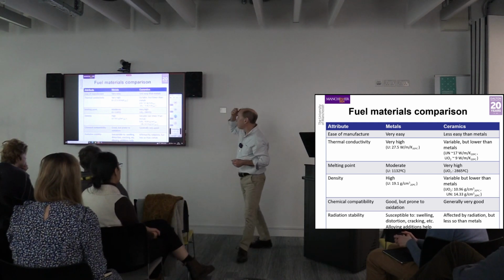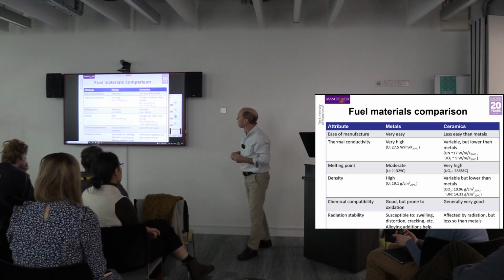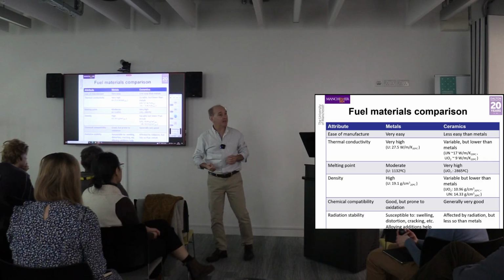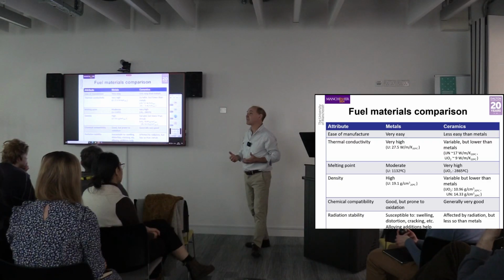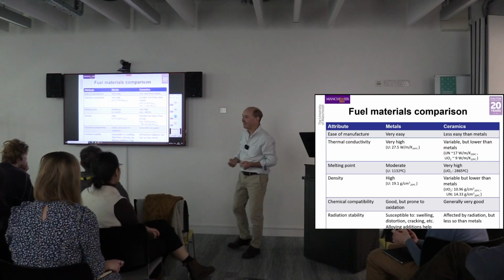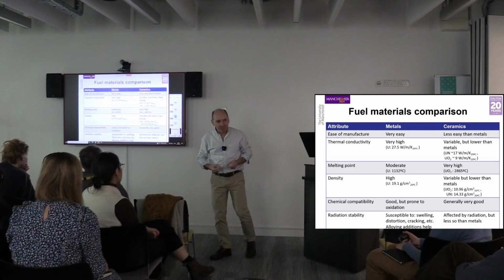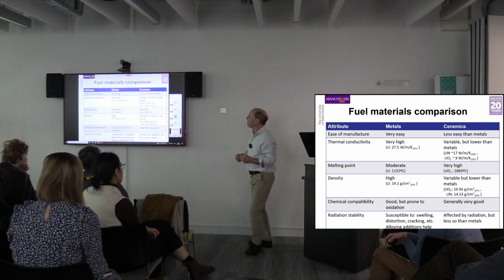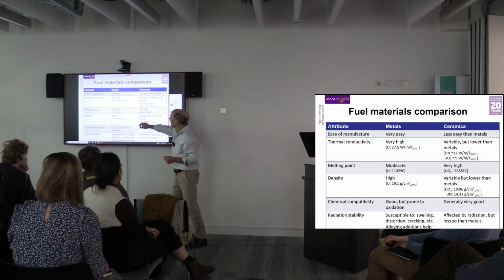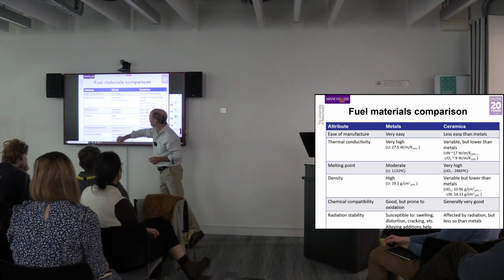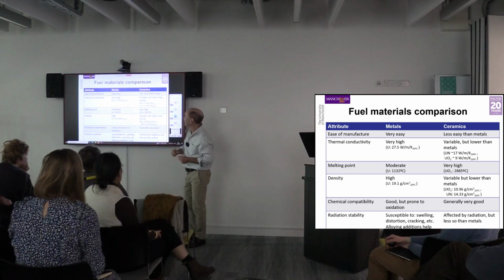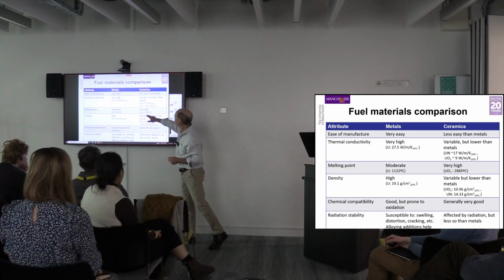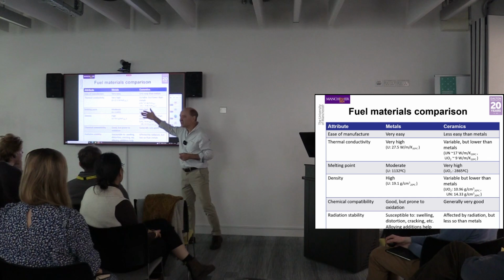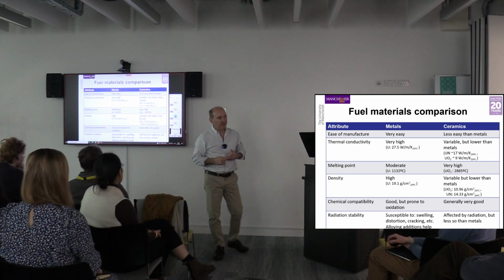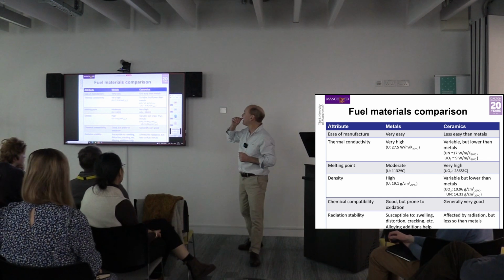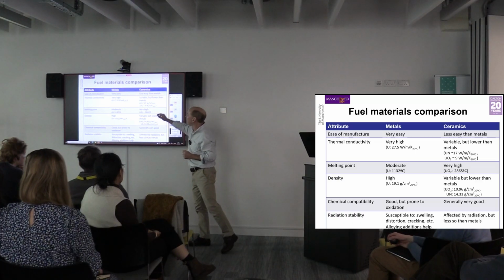Uranium dioxide, it won't surprise you to learn, therefore, on the basis of this, is actually, from a material science point of view, considered to be an insulator. So we make our fuel out of an insulator. That's probably not the best idea until we look at melting point. Metals, well, pure uranium metal melts at just above 1100 degrees C. Uranium dioxide, 2,860 something, depending on which source you look at. So an incredibly high melting point for UO2.